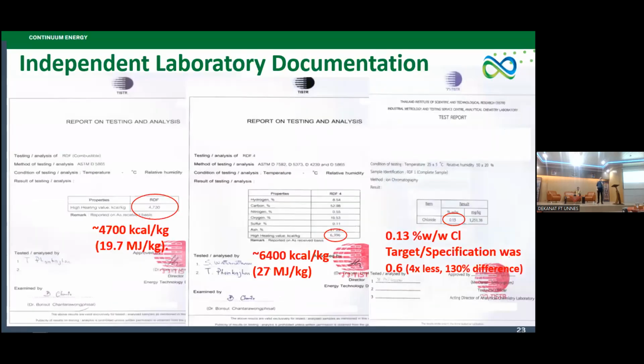So here is the independent laboratory documentation. The first two are the calorific values, and the last one is the amount of chloride. This is particularly important when it comes to environmental pollutants, dioxins, furans, and that sort of thing. Now, conventional RDF facilities in Southeast Asia usually have a chloride weight percent of 0.3 to 0.4, sometimes even higher. The particular cement kiln we were targeting for off-take had a specification of 0.6, but just to show people who think RDF could be good, we wanted to show that it could be clean.